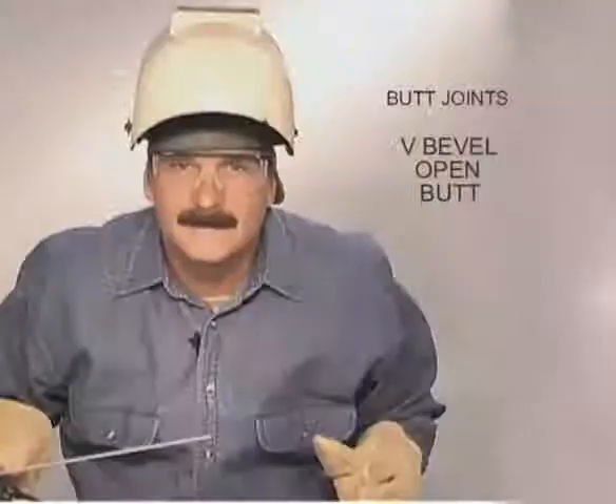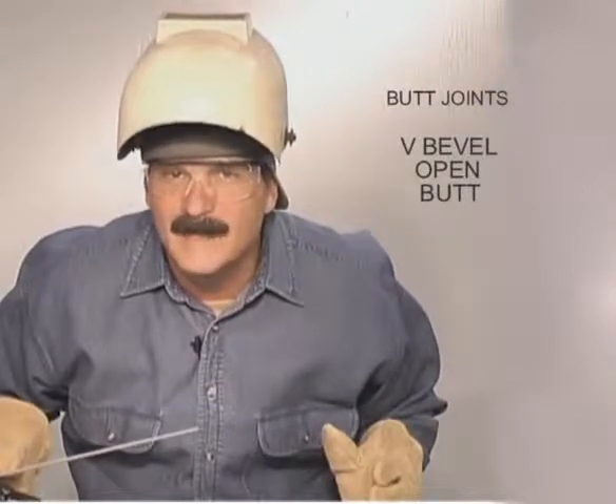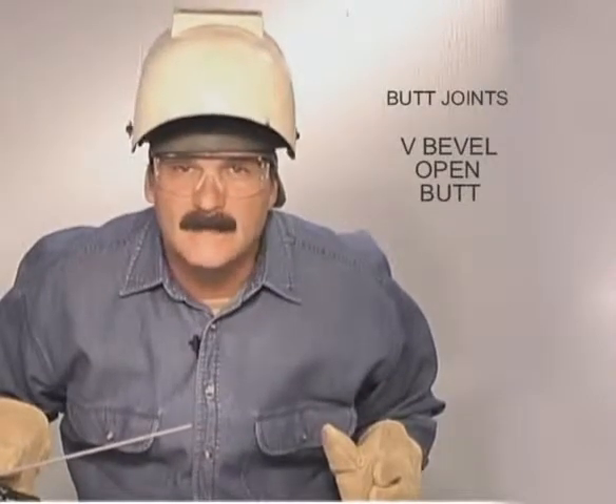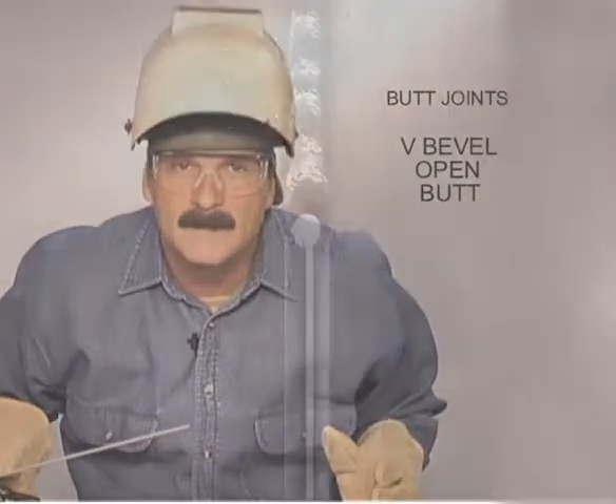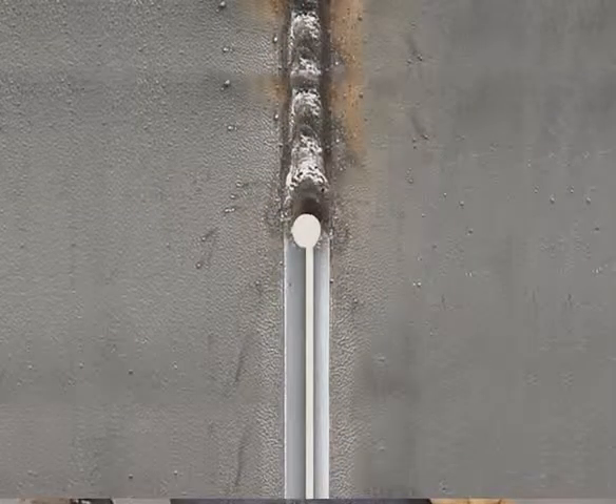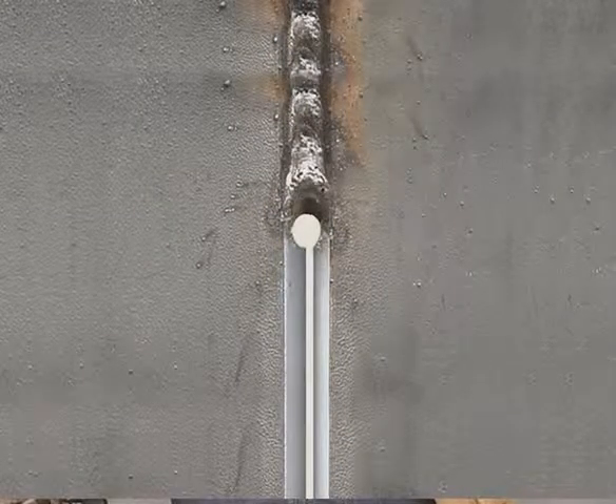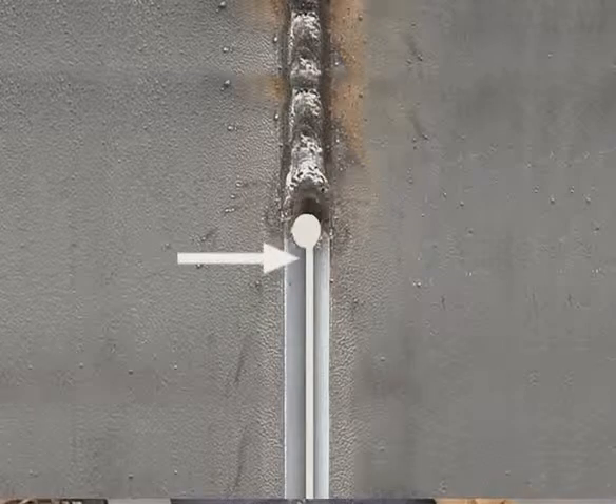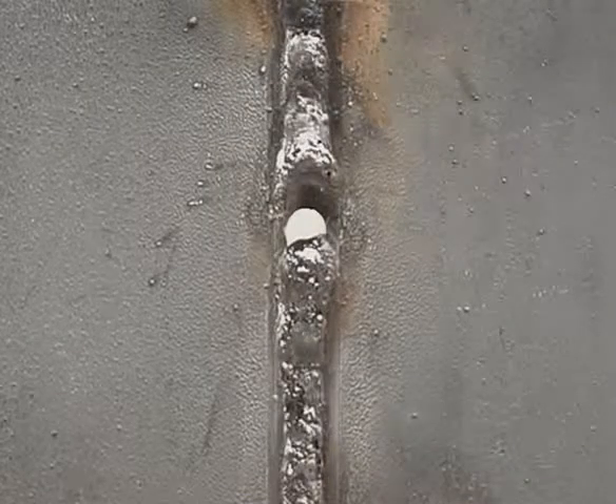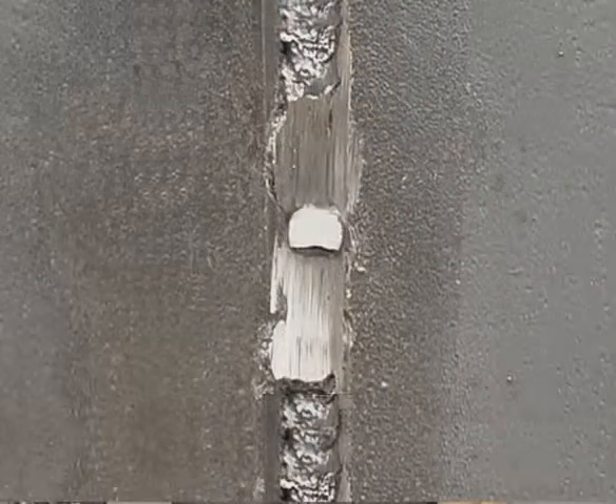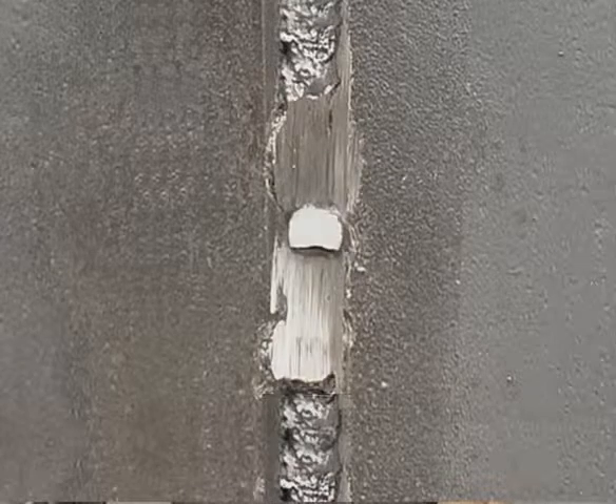Most of the light and sparks will be on the back side, and you're building weld on the back of the metal. You want the amperage relatively high, so try starting about the same place as you'd run flat. If you do open a hole, stop right away, pulling the rod back over the bead. Restart right at the edge and keep going. When you finish the weld, grind the edges thin on both sides of the hole and fill it in.